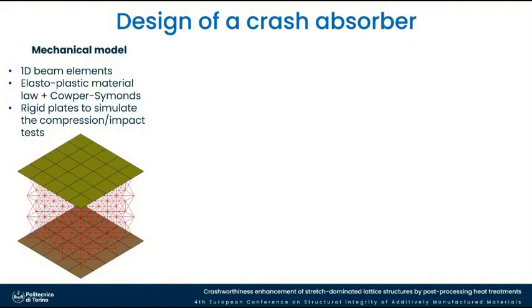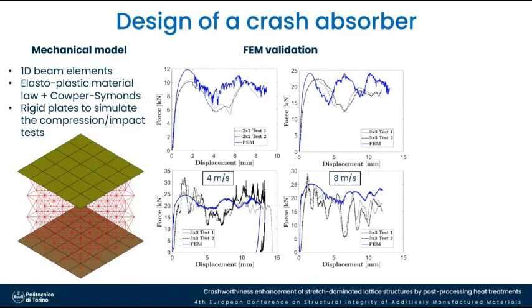And for the design, we start by firstly replicating our test in a finite element environment, using LS-DYNA in this case. We modeled the structure with 1D beam elements. We use the elastoplastic material law that we identified with the tensile test, adding also the strain rate dependency that we identified through the Cowper-Symonds model. And then we validated our finite element model by comparison with the experimental results.